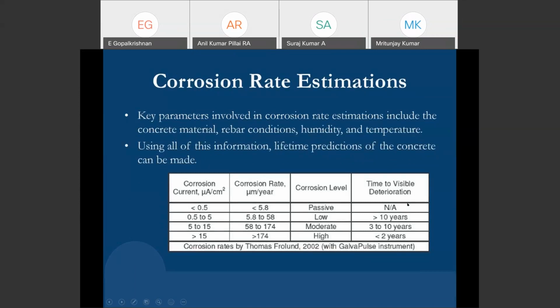The key parameters involved in corrosion rate estimation include the concrete material, rebar condition, humidity, and temperature. Using all this information, lifetime prediction of the concrete can be made. What is the corrosion current, in microampere per centimeter square? We can correlate it to the corrosion rate in micrometer per year, and corrosion level, whether it is passive, low, moderate, or high, with time to visible deterioration of over 10 years, 3 to 10 years, and less than 2 years, where the corrosion current is over 15 microampere per centimeter square.